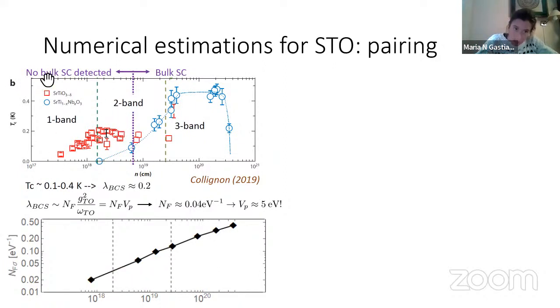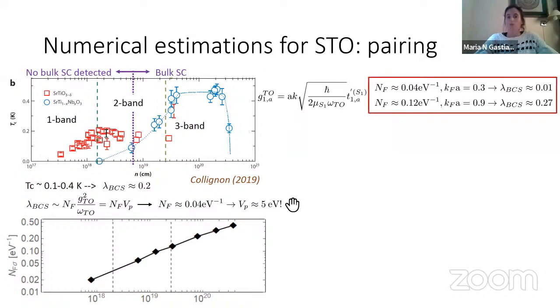Nevertheless, as I said, these are resistive transitions. As soon as you go to this other regime here, where the density of states grows by about an order of magnitude, then this goes down to 500 meV, which is a little bit more into the conventional limits for phonon or Coulombic interactions. So now that I've said this, I go back to our model.